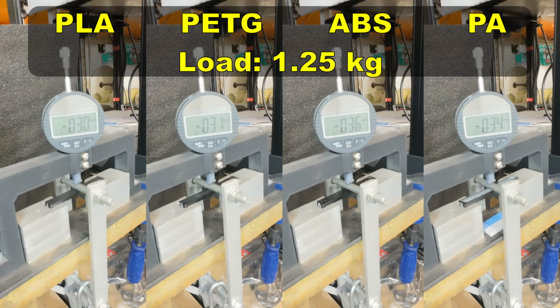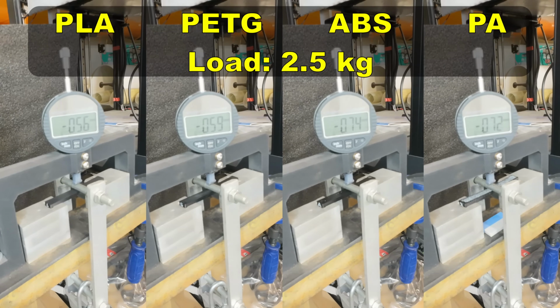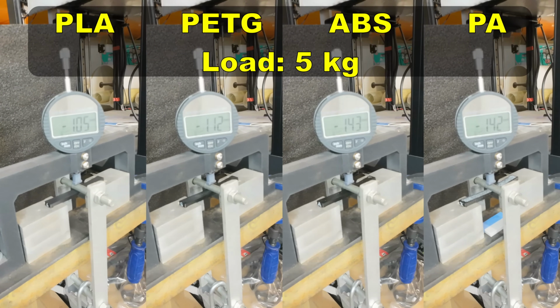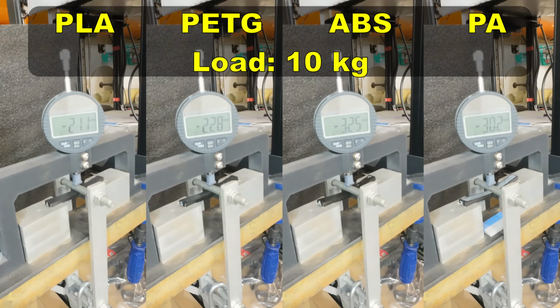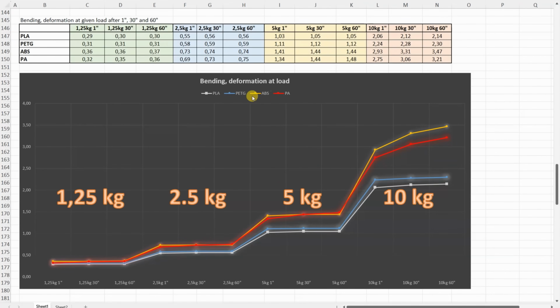3-point bending test. Distance between supports is 50 mm, and I'm placing the loads and I'm measuring the deformation after 1, 30 and 60 seconds. Currently this is under 5 kilograms and the deformation under 10 kilograms. I really like this test because it tells me a lot about any material.